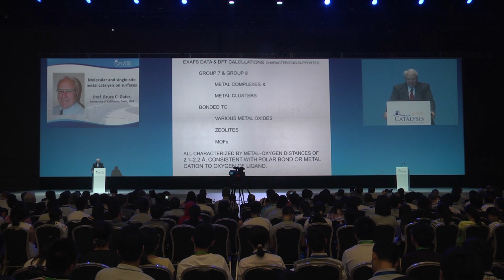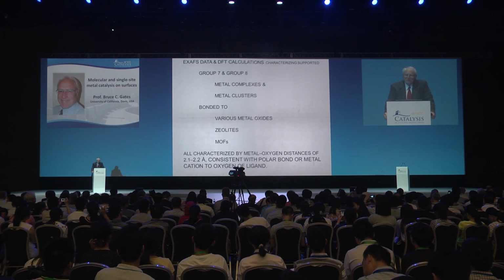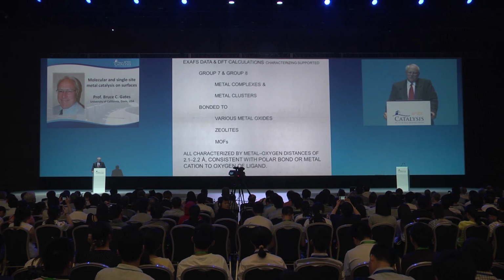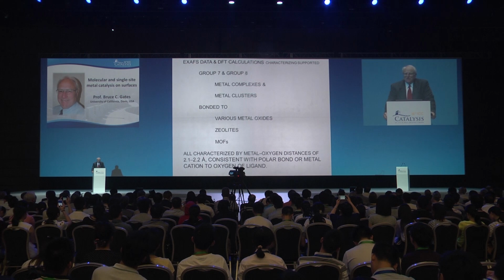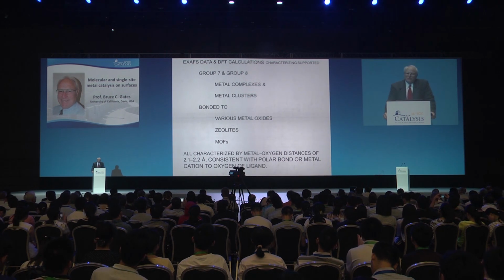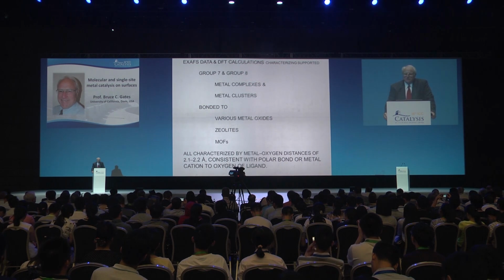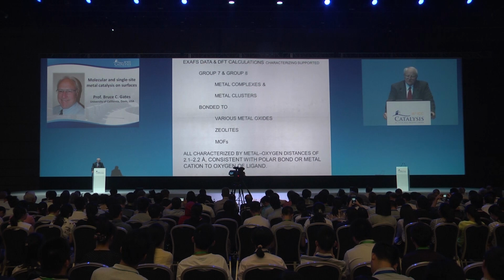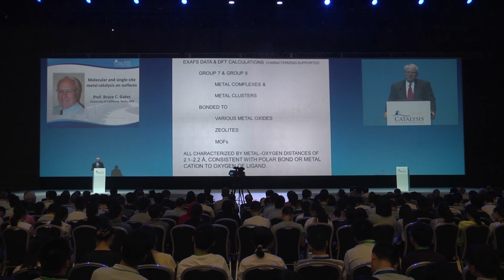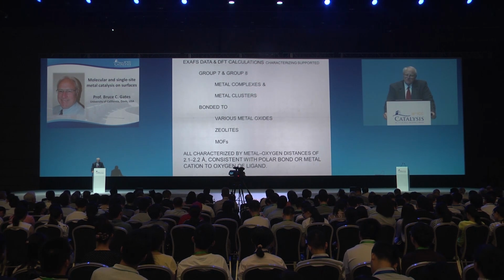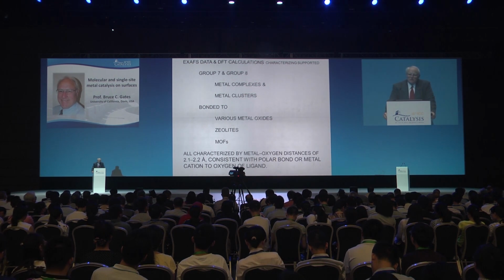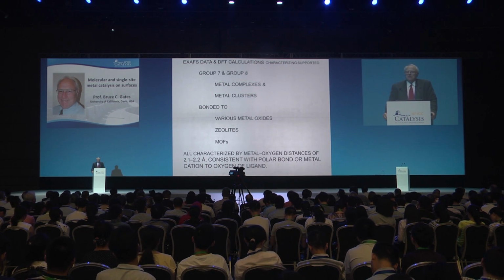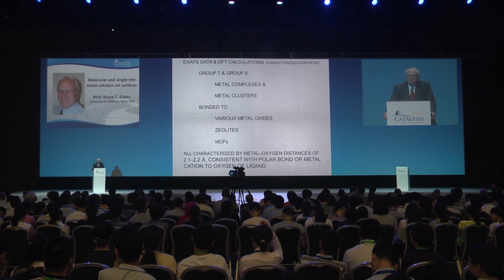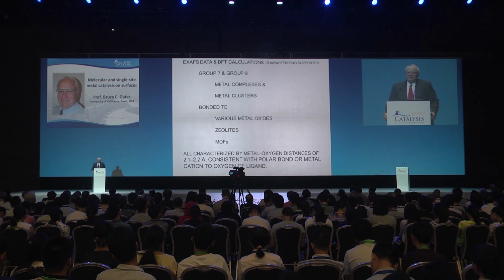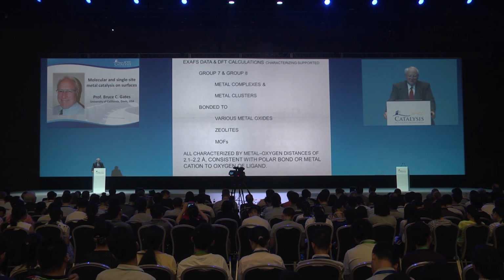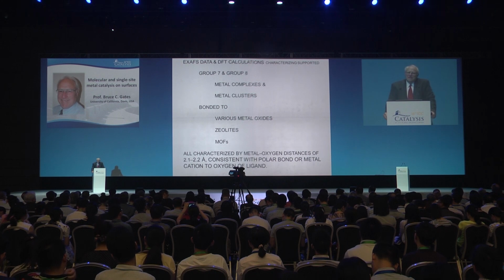Let's look at some other results that have some generality. Look at all the literature, essentially, of metal complexes, cationic metal complexes, metal clusters, on various supports, metal oxides, zeolites, and a whole bunch of different metal oxides, and look at the EXAFS results by which people have characterized these samples. And what consistently shows up is a metal oxygen, that is metal support oxygen distance of about 2.1 angstroms, a bonding distance.